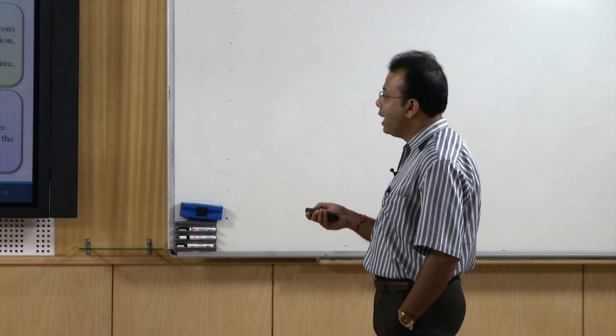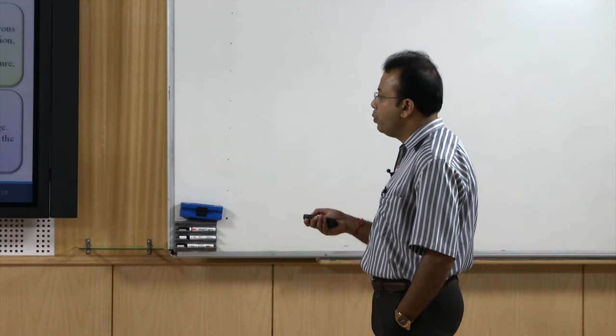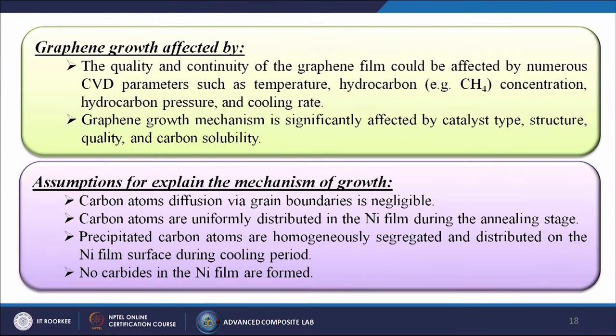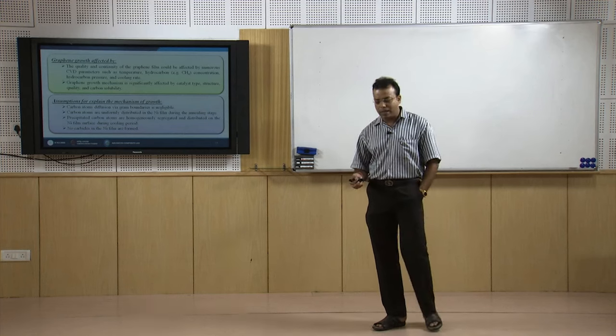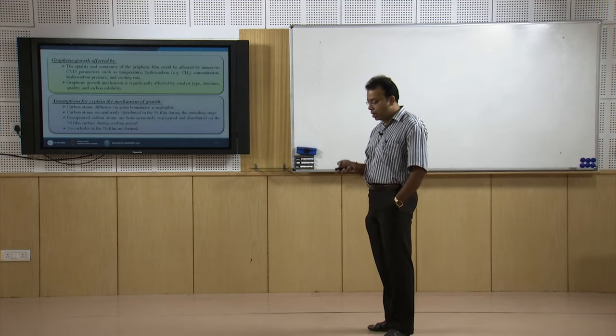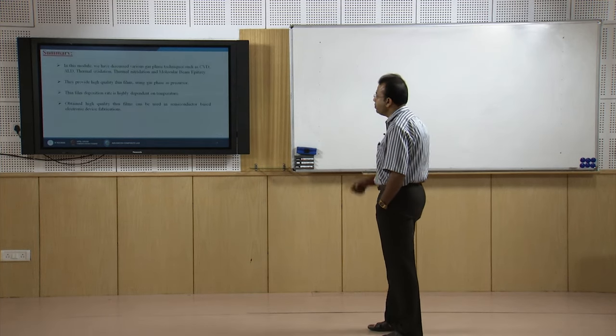Assumptions to explain the growth mechanism: carbon atom diffusion via grain boundaries is negligible. Carbon atoms are uniformly distributed in the nickel film during the annealing stage. Precipitated carbon atoms are homogeneously segregated and distributed on the nickel film surface during the cooling period. No carbides are formed in the nickel films. So these are the different assumptions based on the experimental results.